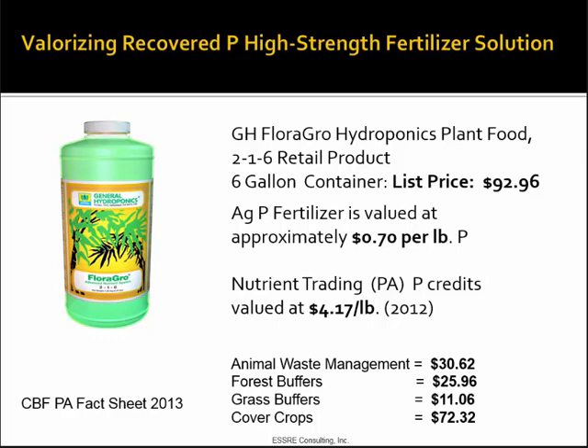We've got nutrient trading credits, Pennsylvania, when they actually were doing dollar value instead of just straight trading, when 2012 was $4, just for the environmental impacts that I talked about. The Chesapeake Bay Foundation put out a PA fact sheet in 2013 comparing P recovery costs or P load reduction costs on BMPs, and they looked at animal waste management at $30, forest buffers at $25, grass buffers at $11, cover crops at $72. So depending on the number of regenerations and the loading rates averaged over the watershed, with the nano material, I could come in at $4 to $11 per pound of P removed, which beats all of the best management practices.